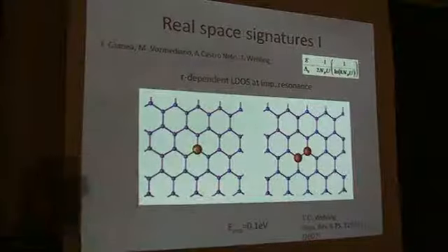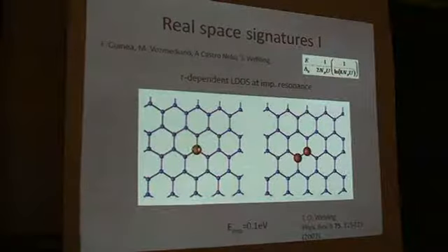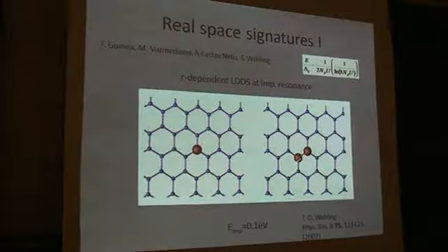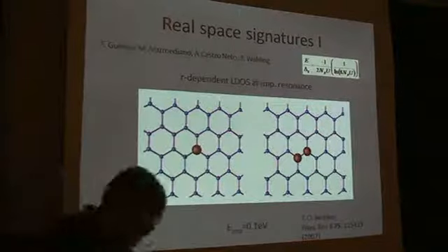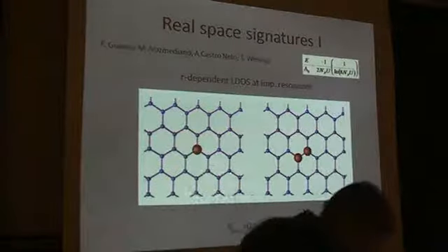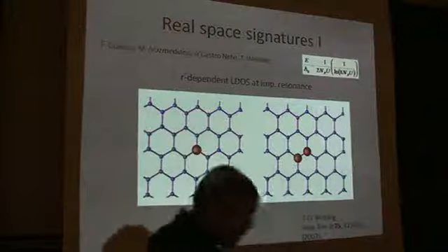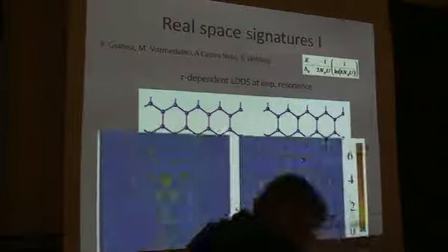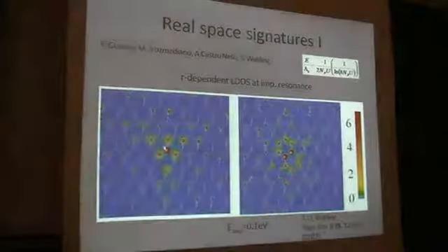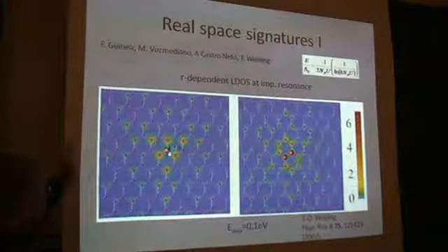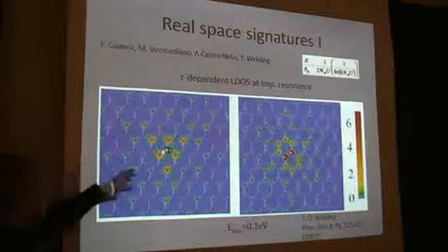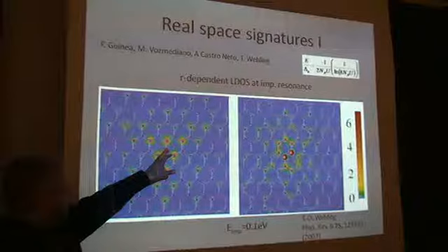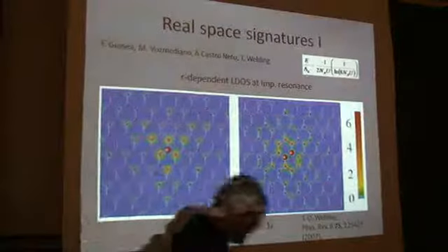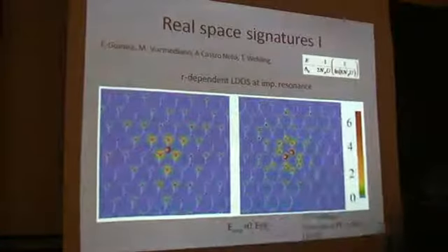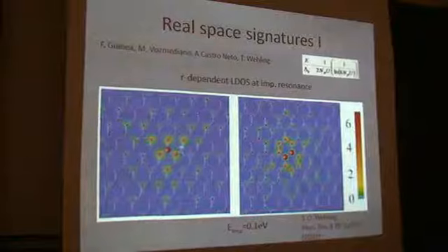So the idea is to use a defect, and in this case we put a very strong impurity potential right on this site, or we can have a couple of them, and see the same story, what the response of graphene would be to these impurities. And sure enough, what comes out is that the story is very similar to what happened in the D-wave superconductor. I have an impurity sitting here, so this site itself works as a unitary scattering center, which drives the wave function of electrons around it to zero.